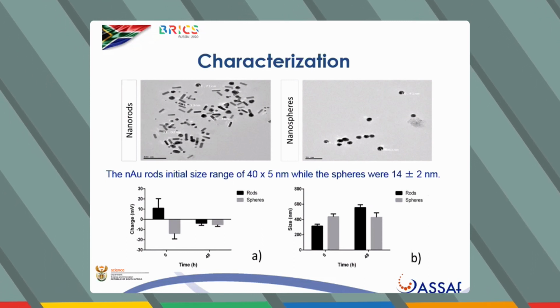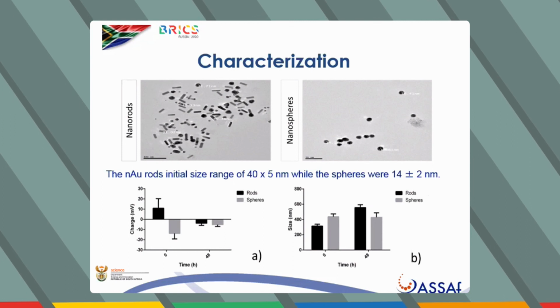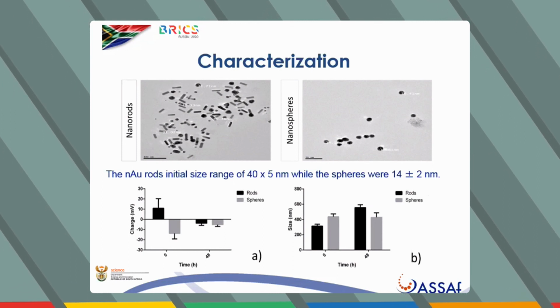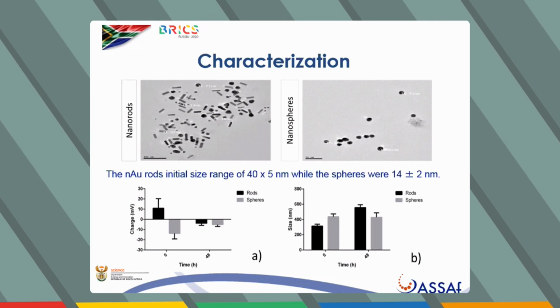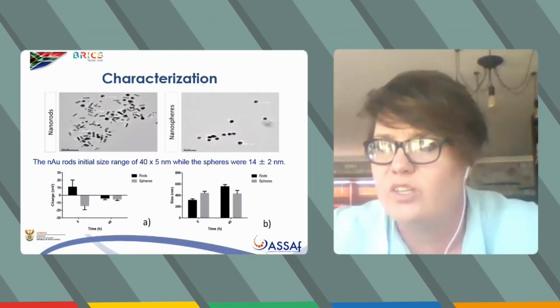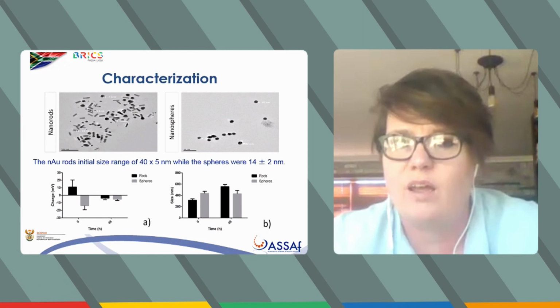And for the spheres, and this is something we've seen across several of our studies, the spheres tend to stay quite stable. They agglomerate immediately in the medium, but then over time that agglomeration doesn't increase, which is something we had not seen with the rods.